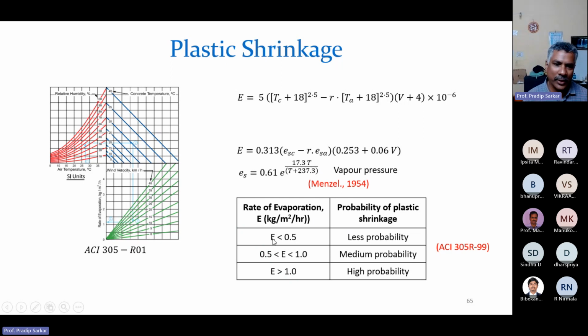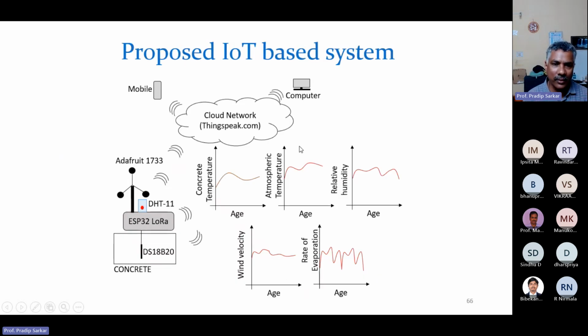And it says that if the evaporation rate is less than 0.5 kg per meter square per hour, there is a low probability of plastic shrinkage cracks occurring. But if the evaporation rate is greater than 1 kg per meter square per hour, there is a high probability. So if we can find out the E value, we know whether there is a problem. So we have set up another device with a wind velocity sensor, and sensors for atmospheric temperature, relative humidity of the atmosphere, and the concrete temperature. All that together lets us find it out.